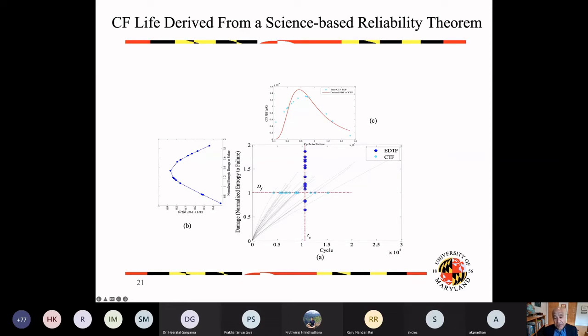And if I take actually these blue data points right here, light blues, which are the time that I reach this micro crack of 250 micron, and if I put a non-parametric distribution over them, this is the distribution that I actually find for them, okay? So this is my derived distribution. This is the distribution that I derive from my observation of markers of damage. The two are essentially very close, identical.